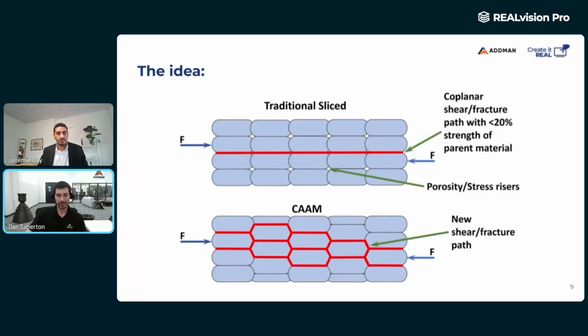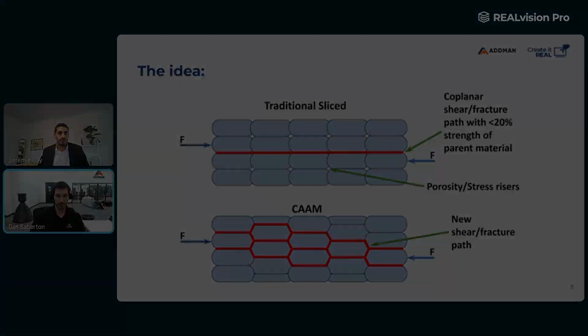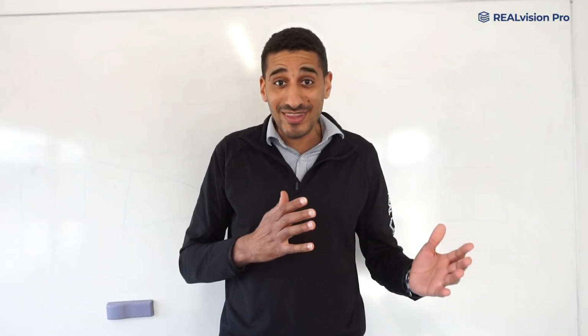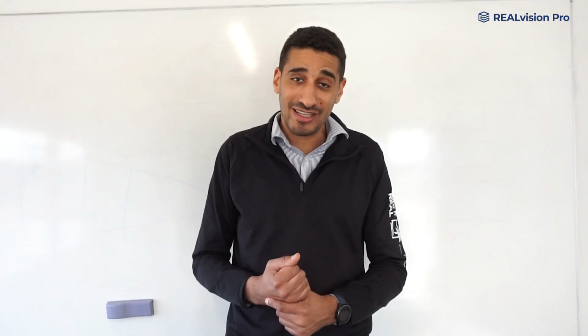The idea of the Interlace technology is this: if you take a look at this red line, it represents the shear path of the fracture through the part. The blue arrows are kind of like a free body diagram of the forces we're putting on the part in a shear type scenario. Most of your FDM parts have less than 20% of the strength of the parent material in the Z direction. Breaking along that XY plane makes these parts very weak. That's a pretty cool idea, but going from the idea to actually implementing it is pretty difficult.